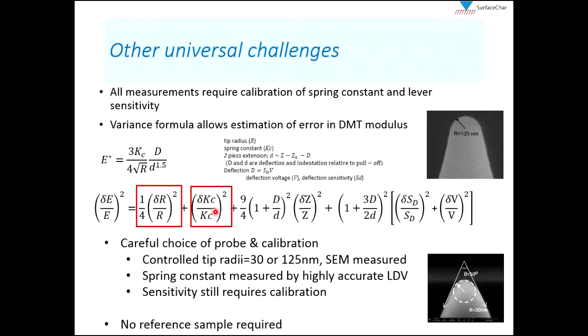So fortunately, there have now been developed some new probes that address this particular area. The first component of these probes is that they have well-controlled tip radii. They come in two flavors, 30 nanometers or 125 nanometers as measured by the SEM. And you can see here the SEM images of these probes. And second, they come with spring constant calibrated by a highly accurate laser Doppler vibrometer. This is far more accurate than the thermal tunes that many of us use to calculate spring constants. So this is a real improvement. Now, our lever sensitivity still does require calibration, and that is done through a static force curve on an infinitely stiff sample like a sapphire. It's a classic method. But at least this way, using these probes, we now do not require a reference sample for the other calibrations.